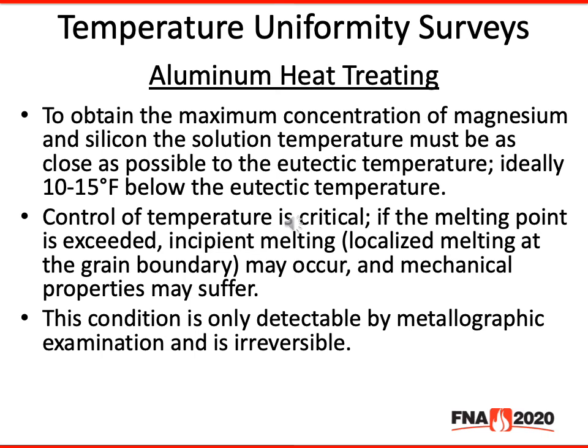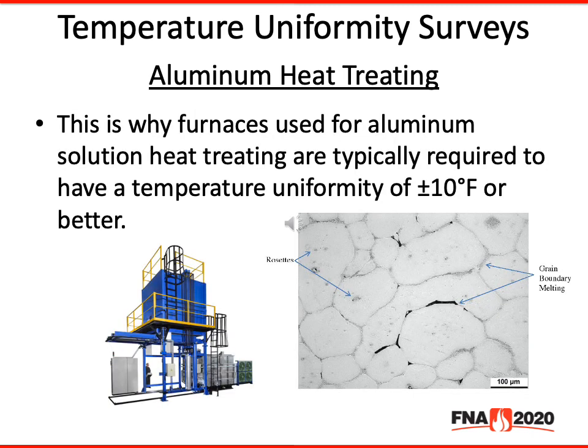Control of temperature is critical in aluminum heat treating. If the melting point is exceeded, incipient melting, which is localized melting at the grain boundary, may occur and mechanical properties may suffer. This condition is only detectable by metallographic examination and is irreversible. This is why furnaces used for aluminum solution heat treating are typically required to have a temperature uniformity of plus or minus 10 or better.